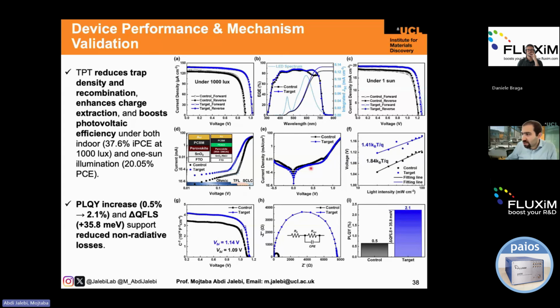This is the dark JV measurement. You can see that especially for the target sample at 0 volts, it's almost orders of magnitude lower current. So that means we have reduced the trap density quite significantly. And this is the JV at different light intensity that shows the ideality factor, and we have a better slope for the target sample versus the reference sample.